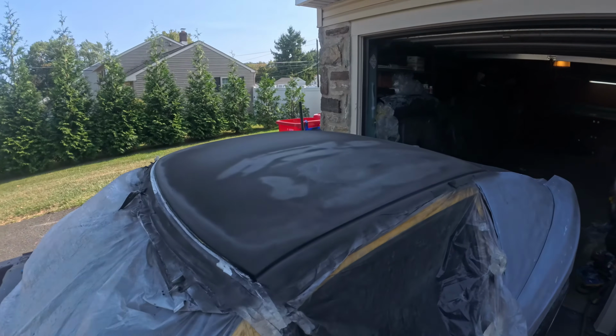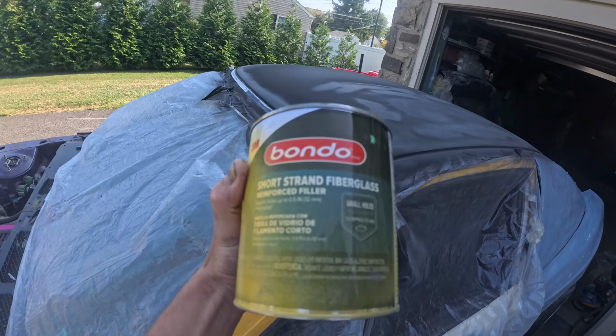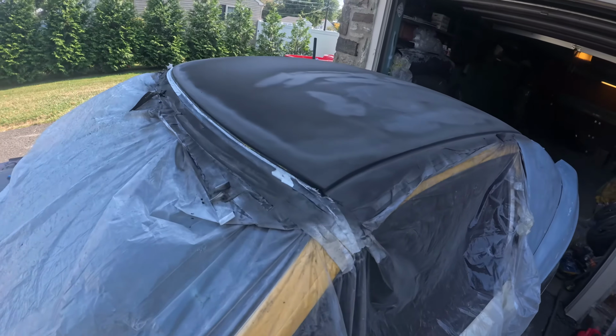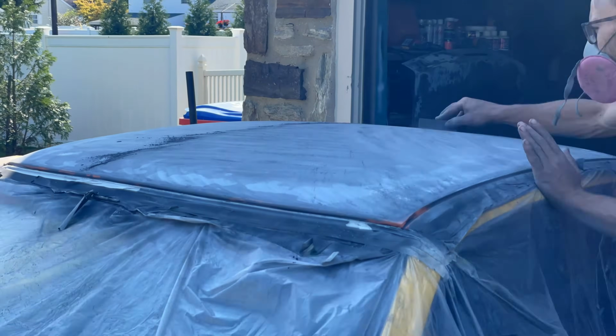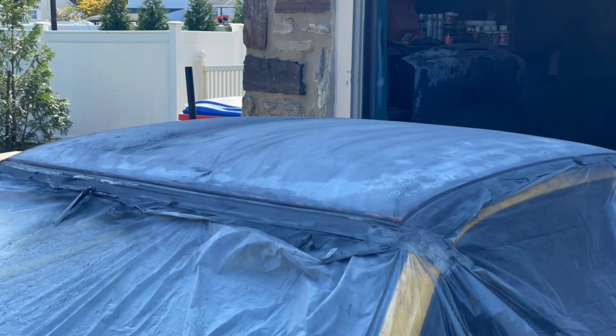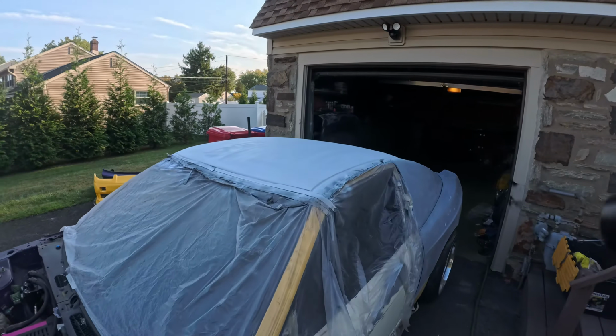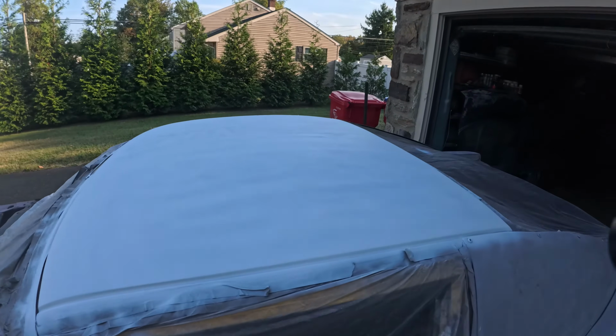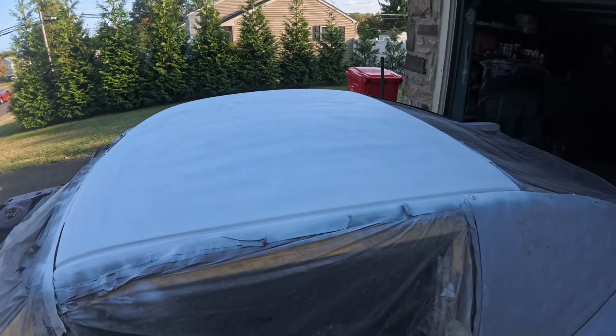Once cured, I molded the front edge of the panel to the roof using some fiberglass reinforced body filler. This eliminated any visible seam and made it look like one single panel. After sanding the filler, I hit the roof with one last layer of primer and guide coat. Once dry, the panel was blocked by hand using 600 grit sandpaper to prepare for the final stage of paint.